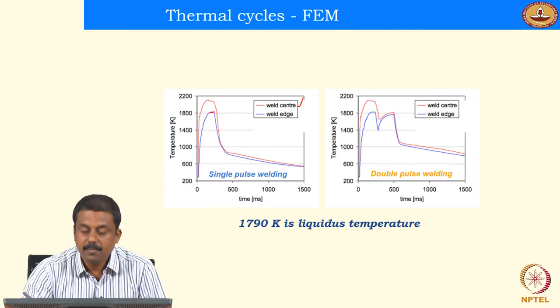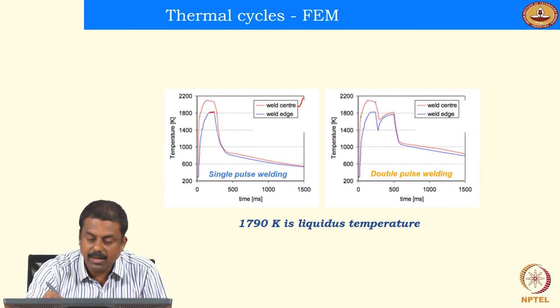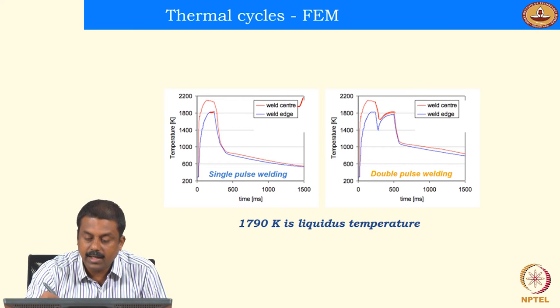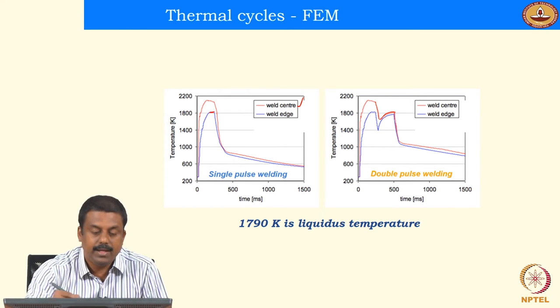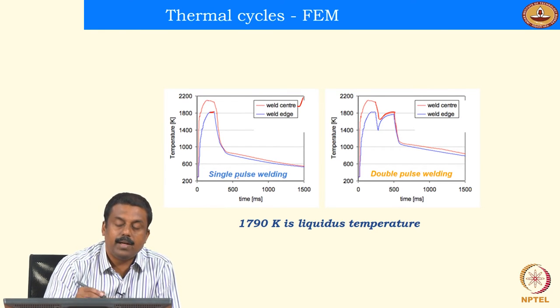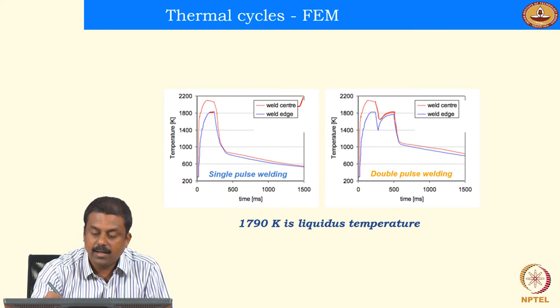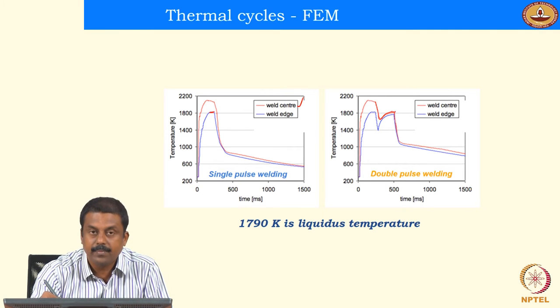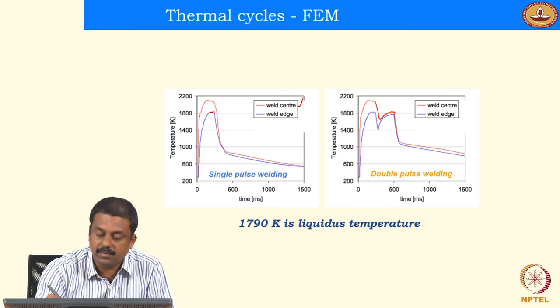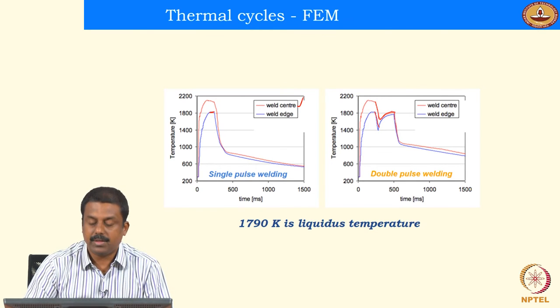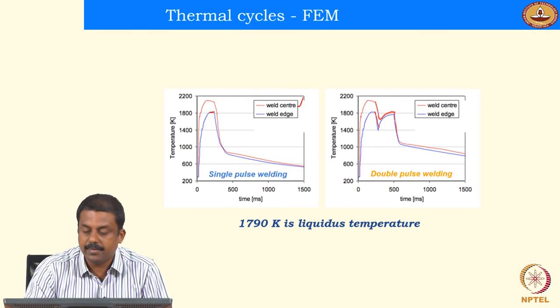And because of double pulsing, instead of cooling after forming a molten region, you cool it to some temperature, and then because of the second pulsing, the material is again heated up to another temperature, and subsequently we cool to room temperature. So we modify the thermal cycle from a continuous cooling from liquidus temperature, and at the weld center, upon cooling to some temperature, we again heat it up like in a post weld heat treatment. Okay, and subsequently we cool to room temperature. The same happens at the weld center as well as the weld edge. One thing is in the weld edge, the peak temperature reached in the first cycle is also lower, and we also have the effect of peak temperatures seen very clearly by comparing the weld center and the weld edge. Okay, so it's very clear, right?